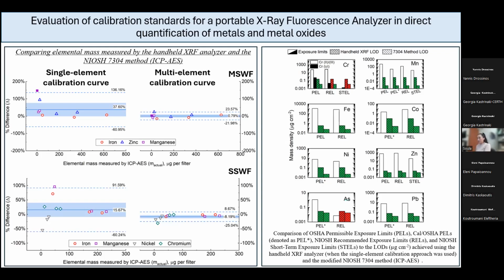In most of the metals, we can successfully detect the exposure limits with any analytical method we use, except for chromium, specifically chromium-6. The recommended exposure limit of chromium-6 cannot be detected when we use the handheld XRF, while the short-term exposure limit of chromium-6 cannot be detected by either handheld XRF or ICP-AES. And also in the case of arsenic, the recommended exposure limit cannot be detected by either technique.